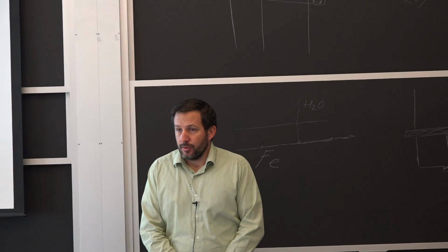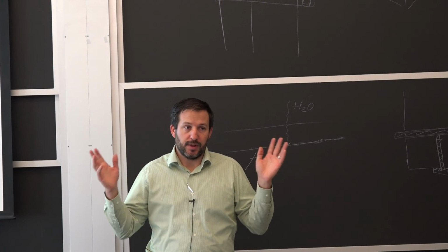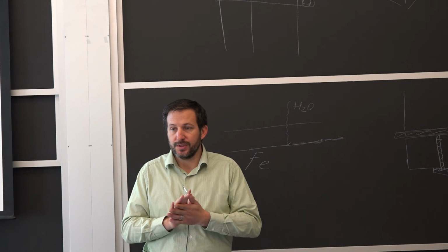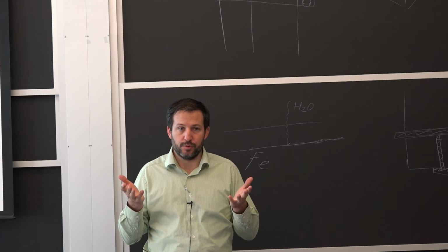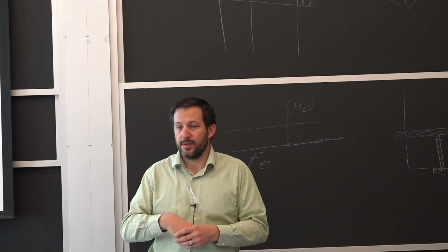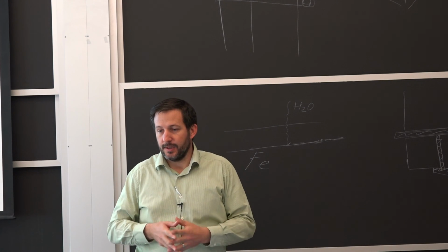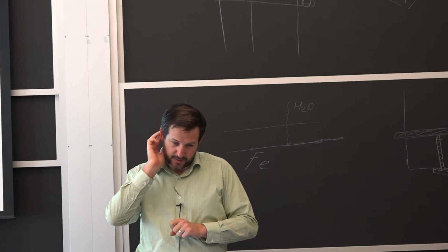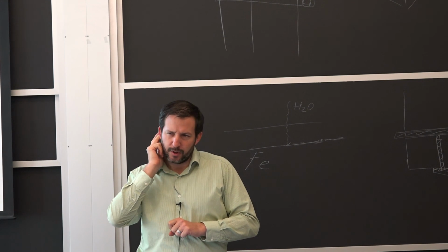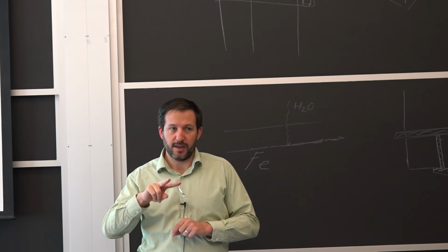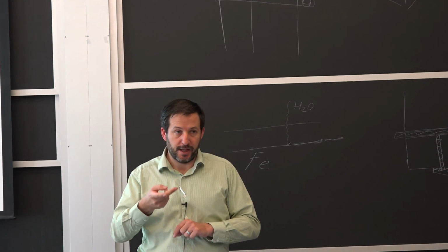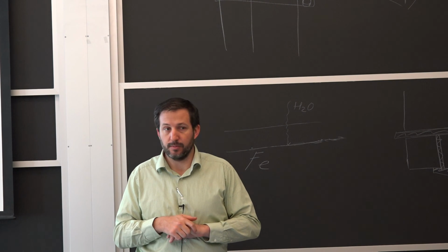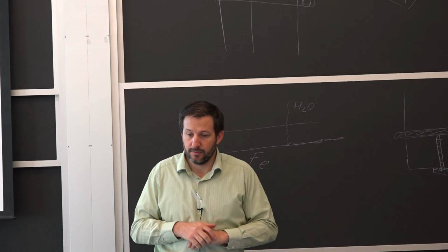If you're talking about temperature exposure, everything becomes a different situation. So a lot of stainless steels are going to become at risk for stress cracking at elevated temperature. So if you're thinking, okay, well, this is a piece of stainless steel for a boat or a sailboat or anything like that, then that's fine. But if it's a pressure vessel for chemical processing, a lot of times it's surprising that they have to switch back to regular steel and handle the fact that it's going to corrode, to lose section, just so they don't have these brittle cracks, the stress corrosion taking place and then having failures related to that.